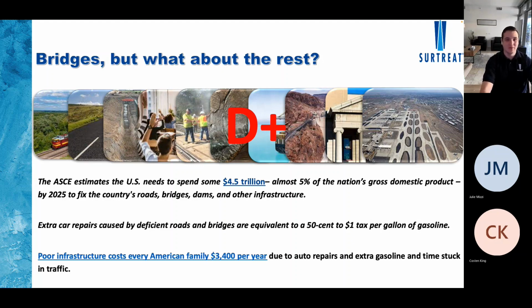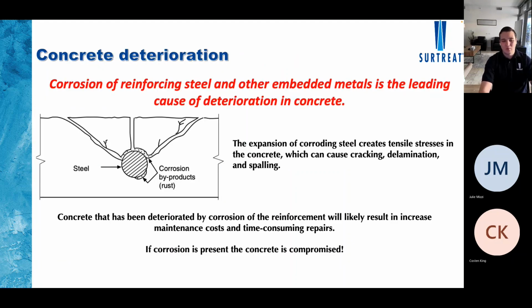It's hurting people, regular people. Now, why is this happening? Now, the main cause of concrete deterioration is corrosion of reinforcing steel. When reinforcing steel starts corroding, what happens is that corrosion starts creating a tensile stress on the rebar and on the concrete. So as the corrosion expands, the concrete gets that expansive tension and starts cracking and delaminating.